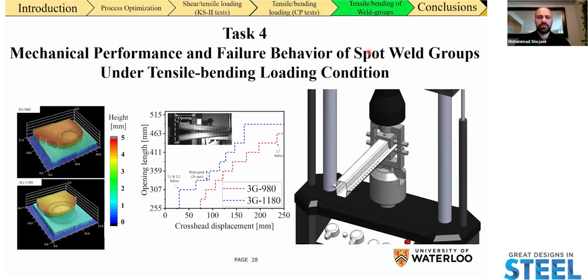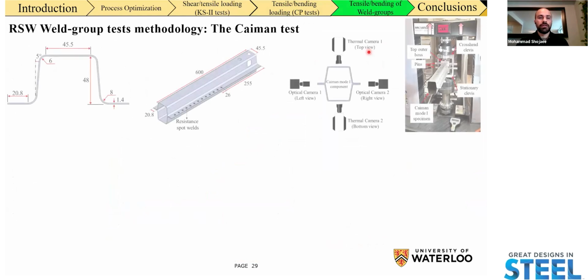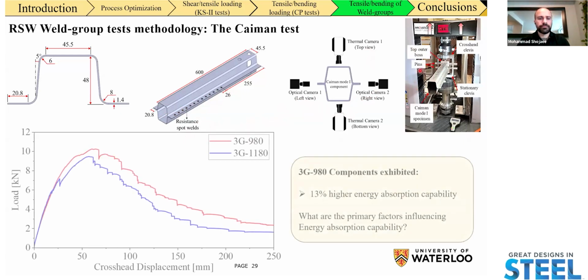Now, coming to the last chapter of my results, where we deal with the component test under tensile bending loading conditions characterized by the Caiman test. You can see the methodology of this test in this slide here, where we're using two hat section channel rails. We coupled all of the tests with optical cameras and thermal cameras to track the onset of failure for different spot welds that are located along the flange. You can see the fixture that we use to perform these tests on our tensile frame.